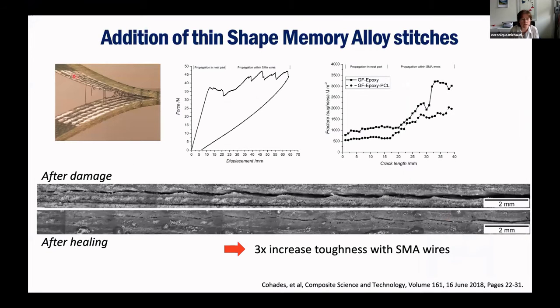And if you see here, this is a DCB test. You see the stitches here are completely broken, of course, that's not the idea. But if you don't break, after damage, you see here you have a big crack. After healing, so the shape memory alloy wires, they actually heal the crack, so they help to close the crack, sorry.